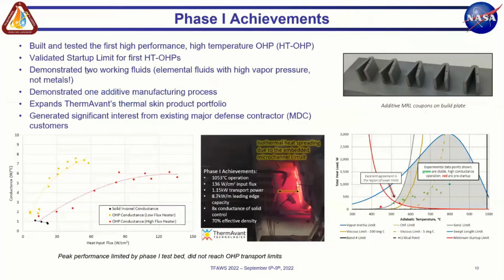And demonstrated 2 working fluids during that phase 1, and these, to the surprise of most people, were not liquid metals. These are different elemental fluids that have high vapor pressure. Demonstrated a manufacturing process, so a little bit of MRL development in the phase 1 to prepare for the desire to produce wedge geometries in phase 2. All the phase 1 testing was testbed limited, did not reach any OHP transport limits, but we were able to demonstrate these key characteristics shown in bullets, get up to just over 1,000 degrees at the input surface of the Inconel envelope, input flux a little over 100 watts per square centimeter at the evaporator, 70% effective density of the outer envelope of the same geometry Inconel due to the void space and the lower density fluid charged inside, and approximately 8x conductance of the envelope itself.